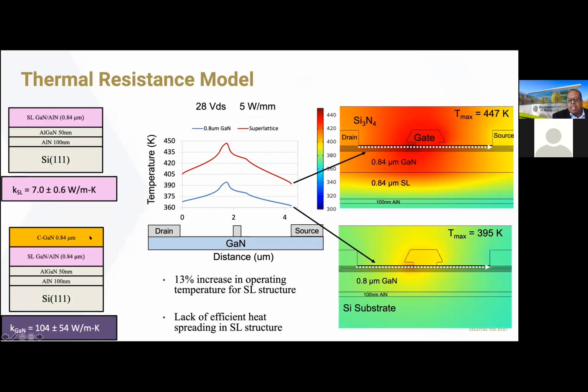We measure the thermal conductivity of this thin gallium nitride layer. It's on the order of 104 watts per meter K. And you put that into a model, and basically what you see is that you do get a reduction in temperature between the two. With a superlattice structure, it's going to be hotter than if I don't have one. But you also see this confinement of the heat really close to the channel region, whereas this is spreading out. So this is giving us an idea that we need to build some heat spreading into the device structure in order to counteract the need for this superlattice structure, which is basically helping us to control stress.